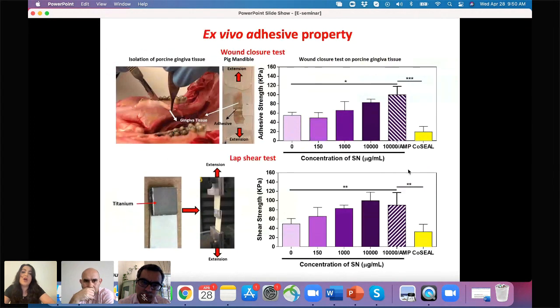So here are some data based on ex vivo tests. We wanted to measure the adhesive properties of this hydrogel to the gingiva tissue and also to the titanium. Here are different formulations of the hydrogel. This is the gel without Laponite and without AMP, and then we added different concentrations of Laponite and antimicrobial peptide, and we measured the adhesion strength of the hydrogel on the gingiva tissue based on a wound closure test, and on the titanium surface based on a lap shear test. We show that the adhesion increases as we introduce these nanoparticles inside our hydrogel formulation.